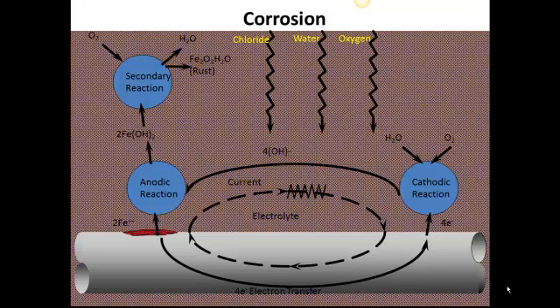Looking at the image on the screen now, you can see that in order for corrosion to begin, you have to have water and oxygen at the level of the reinforcing. You also require the ingress of chloride salts. The reason the ingress of chloride is required is that reinforcing bars in concrete are surrounded by an alkaline environment which forms a passive coating on the reinforcing bar preventing corrosion. This is why concrete and steel work very well together. The chlorides, which diffuse slowly into the concrete or travel quicker along a crack or other break, break down this passive coating and allow corrosion to begin.